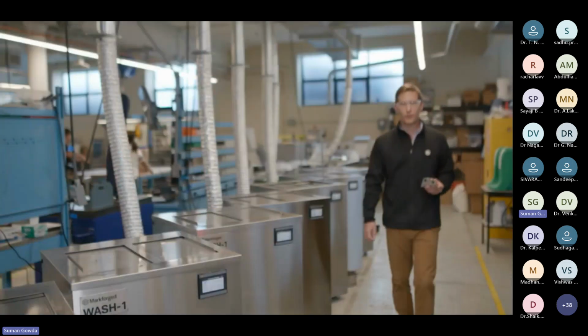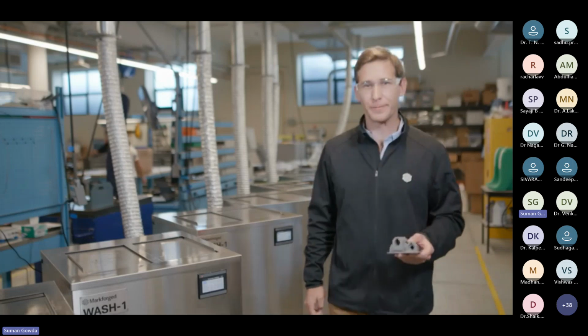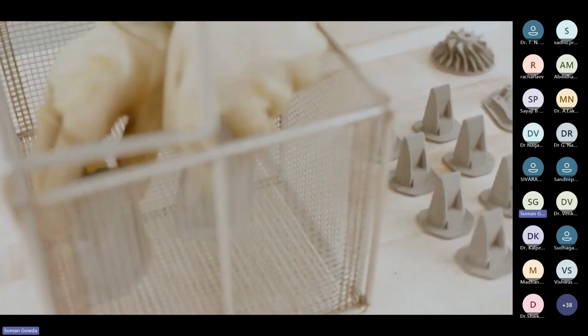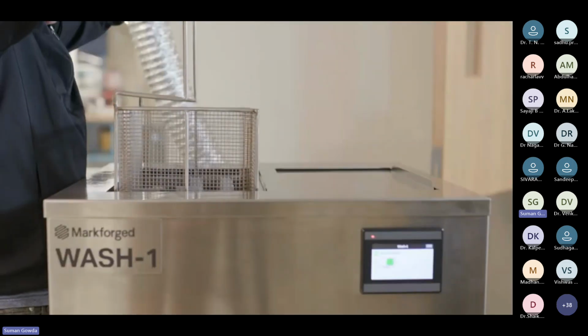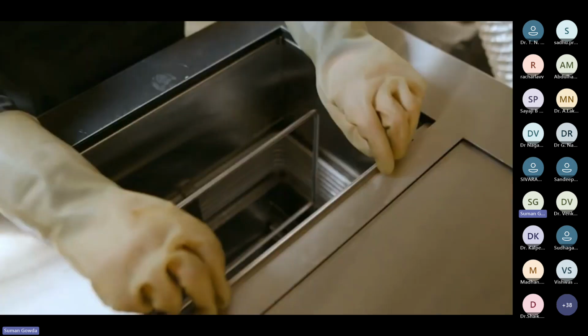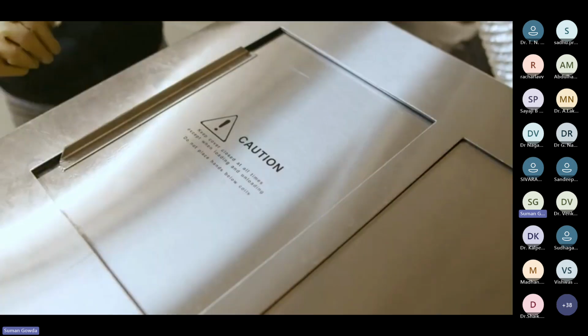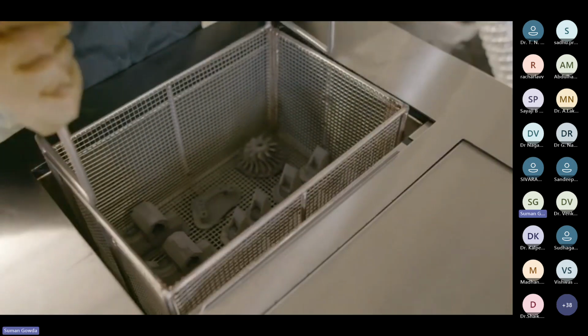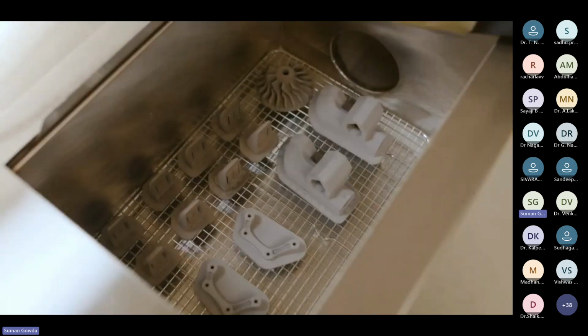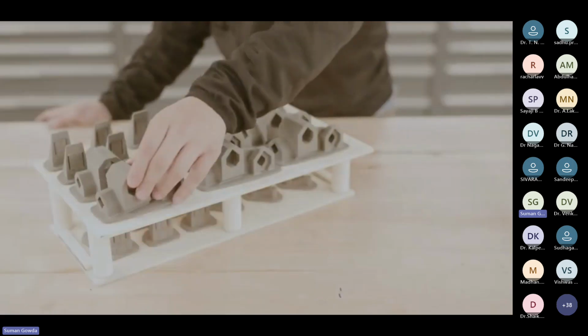Wash 1 removes the first stage of the binding material. A green part is taken from the printer and placed into the wash basket, which is then lowered into the solvent. Wash times will vary, ranging from a few hours to a few days, depending on the thickest region of your part. After that, it's now called a brown part and is ready for sintering. Let's go over to the furnaces.